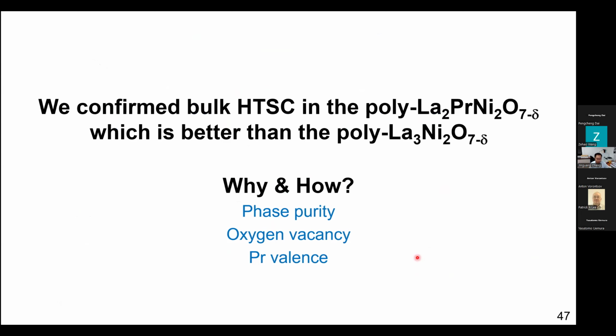So basically, we observe zero resistivity and diamagnetic signal. These two characteristics of superconductivity in the praseodymium doped sample. And it seems that the superconductivity is much better than the undoped sample. So why is the doped sample better? And if we can figure out the reasons, probably we can design better bulk high TC superconductors. So in the following, I will show you some of our characterizations.